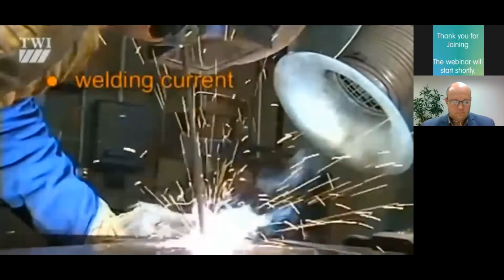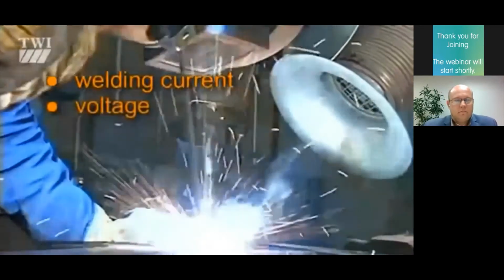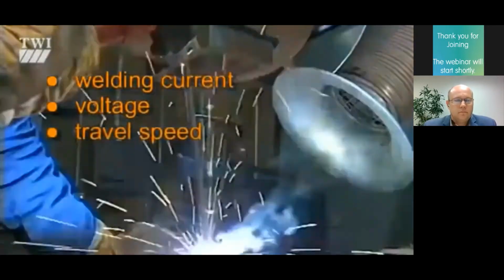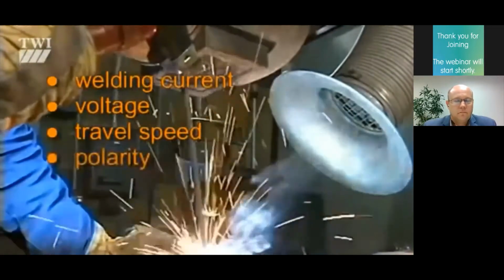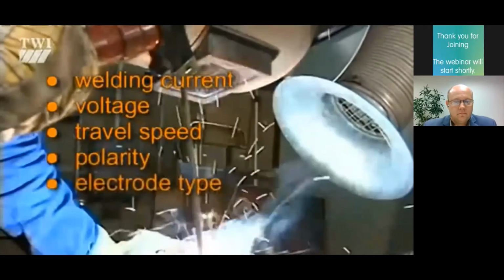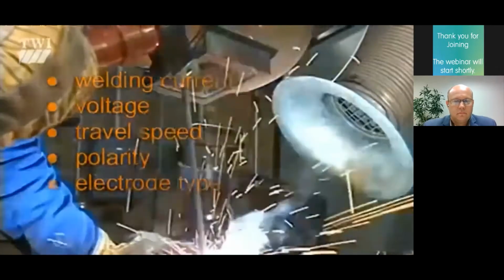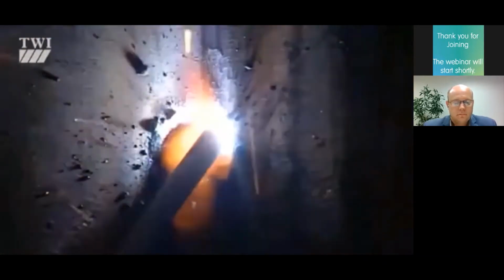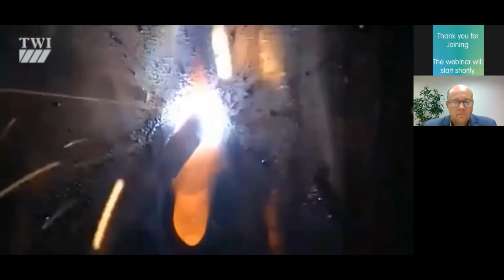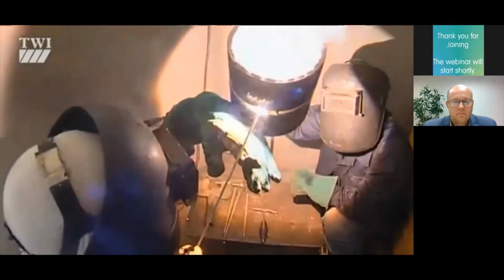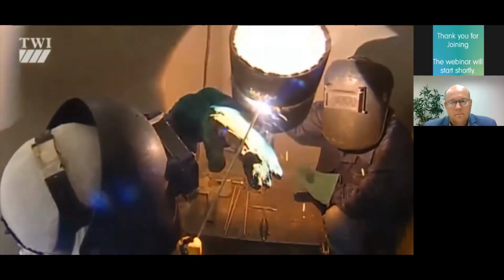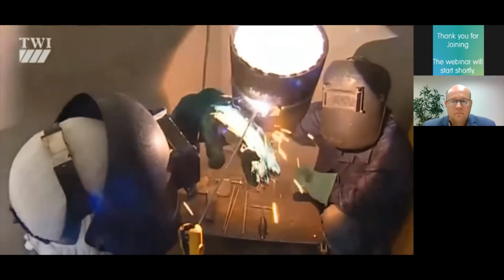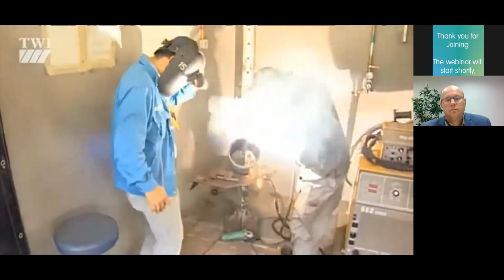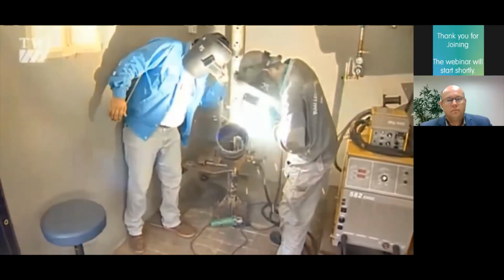The variables which affect the final quality of the MMA weld are current, voltage, travel speed, polarity, and electrode type. So, among the pluses, MMA is ideal for field or workshop use. The kit is very portable and simple, and the process is all positional. On the downside, it requires a high skill factor. It's susceptible to slag inclusions, and it generates lots of unwanted fume.